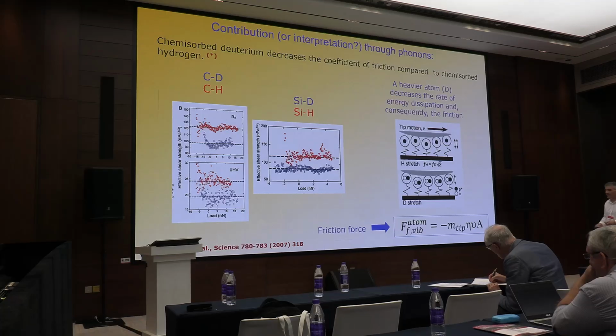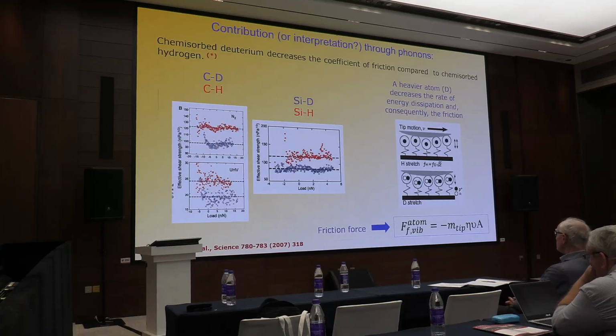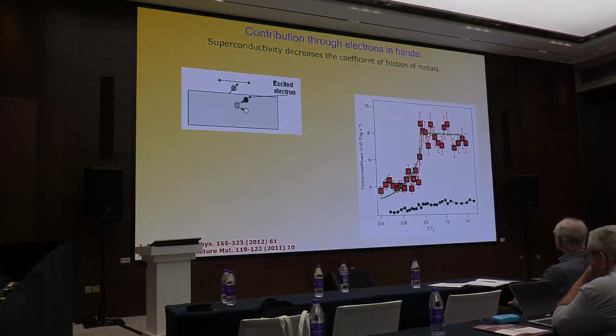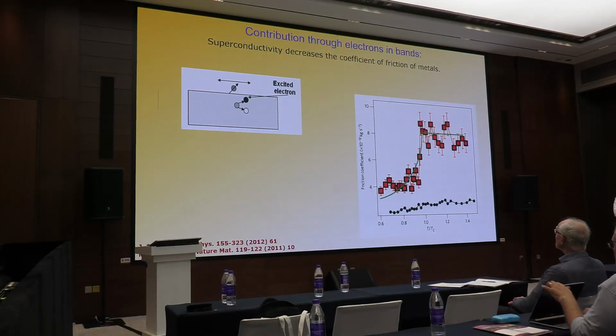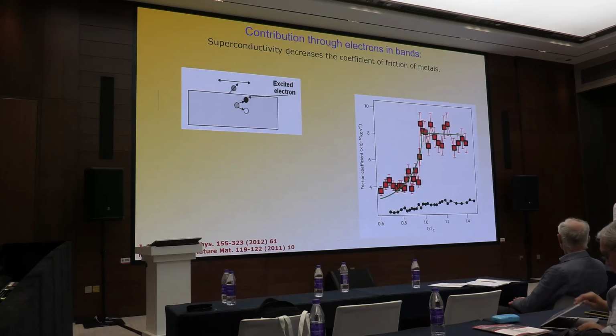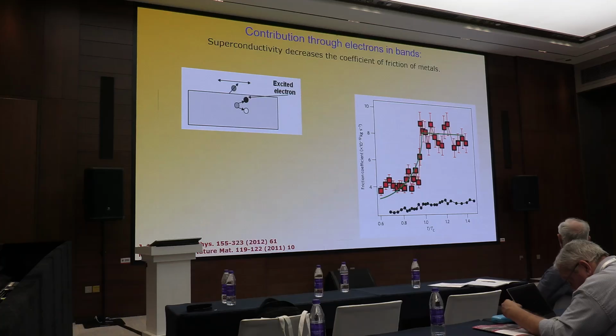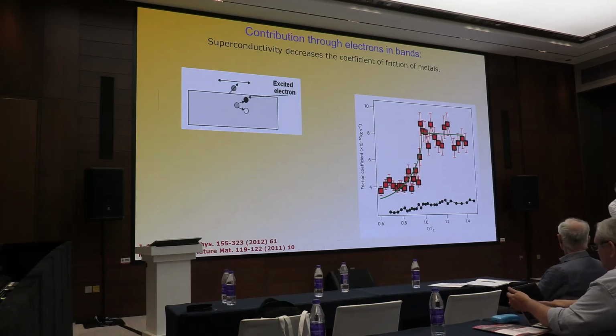The point is, in this expression, what is the origin of this expression? I will explain that. I explain this phonon explanation of phonon contribution to friction, because the hydrogen and the deuterium vibrate on the surface and dissipate. This is the idea. According to this author, when you have a slower vibration, as with deuterium because it's heavier, you have less dissipation. When you have a higher vibration, you dissipate more.